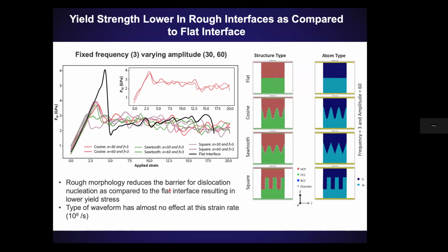So the 4 different shapes that we looked at were a flat interface, a cosine interface, a sawtooth interface, and a square interface. The things that we changed: we kept the frequency the same, changed the amplitude, so made the waves taller versus shorter, but kept 3 of them in all these cases. The first thing to notice is that that flat interface in general tends to have a pretty high yield strength as compared to these rough interfaces. In fact, we wanted to understand why.